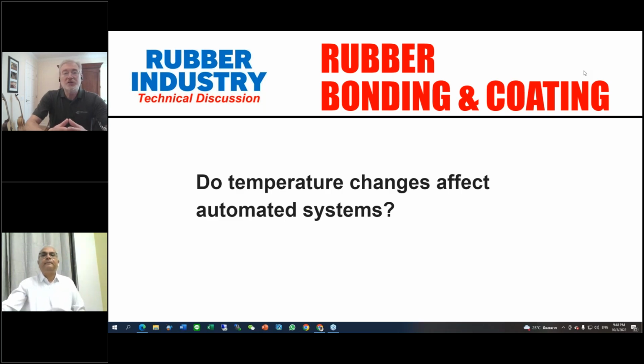So changes in spray pattern or in spray consistency, atomization, things like that happen as a function of temperature-based viscosity changes and will have a significant impact on an automated system. And if it's creating a defective film, it will repeat that process part after part after part, just the same as it can repeat a good part. So yes, maintaining viscosity by maintaining temperature is essential in automated systems. Does that help? Ravi, do you want to add anything here?